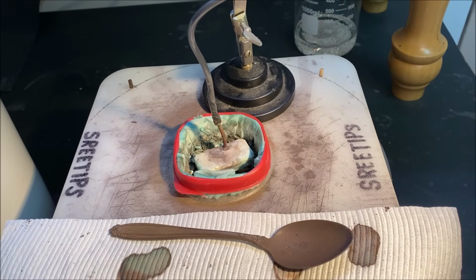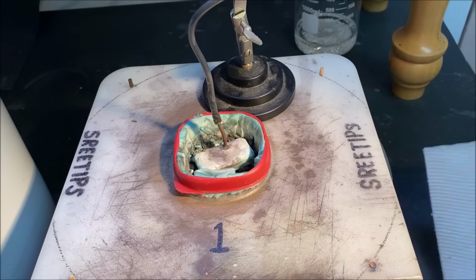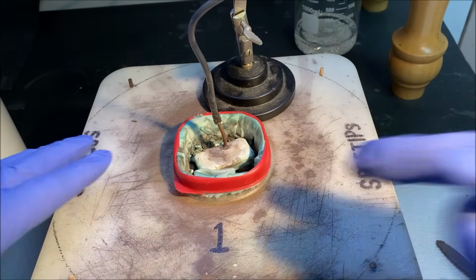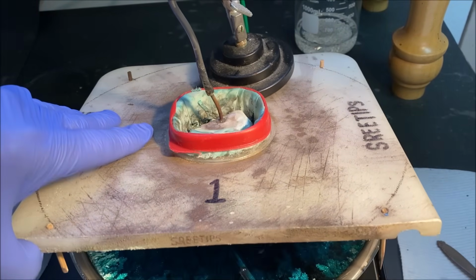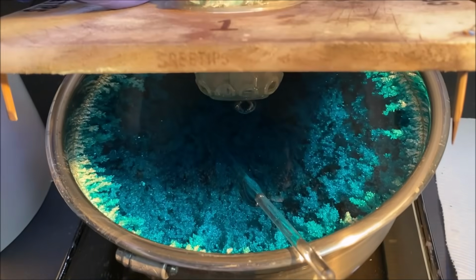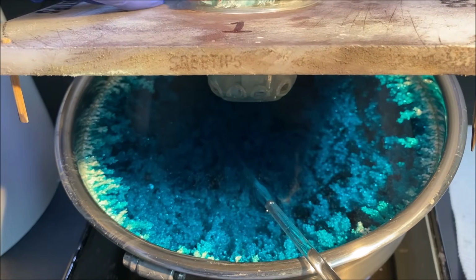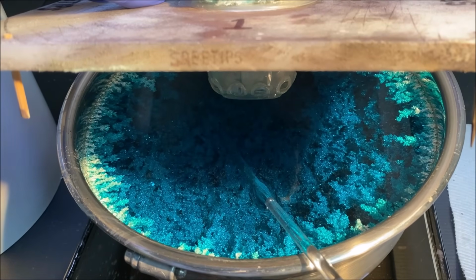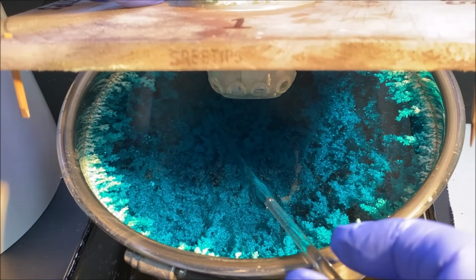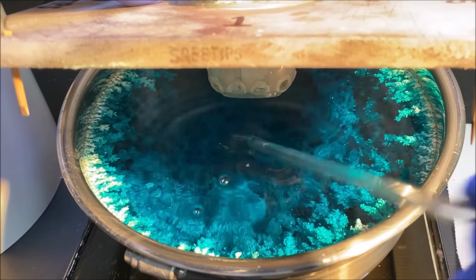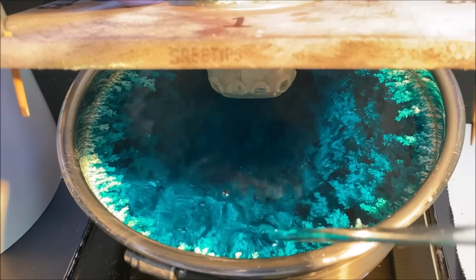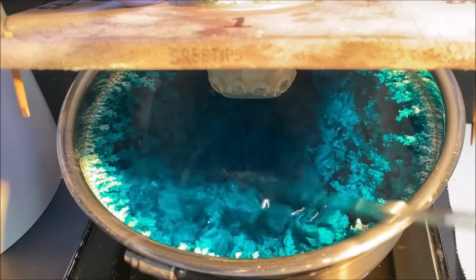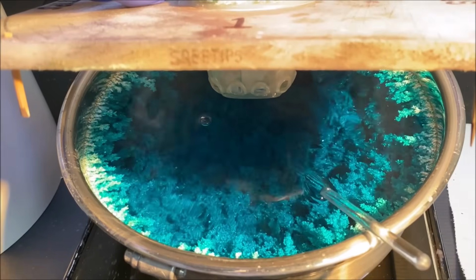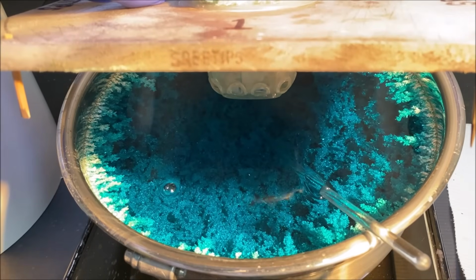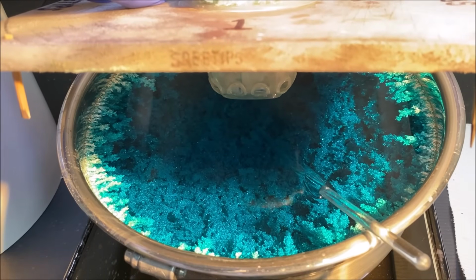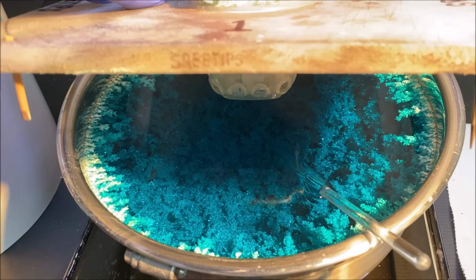And the purpose of that fuse is to blow the circuit in the cell if the silver crystal reaches up and comes in contact with the anode filter basket. It'll short it out, and it'll ruin the batch of silver. The slimes from the anode basket will leak down into the silver cell down here and ruin this batch of silver. This is about 2 weeks worth of growth. Should be about 2 kilos of pure silver in here.